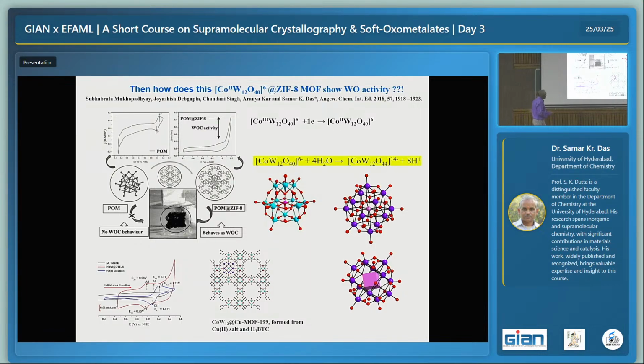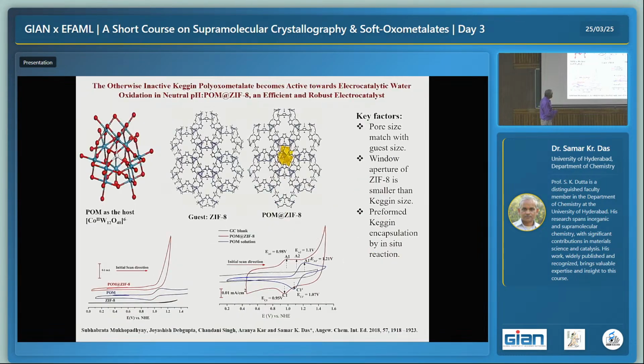So we believe that this is the compound formed, and that gives both couples, cobalt 2/3 and 3/4. Now it makes sense why upon encapsulation it gives oxygen evolution by electrochemistry, because we believe the cobalt cluster hydrolyzed to this cluster, and now this gives 2 couples, cobalt 2,3 and cobalt 4,3 and cobalt 3,2. Now you may ask me, how do you know this compound will give these 2 couples? Because now it is published by others. They synthesized this compound and did the CV of that compound, and it gives exactly the CV we got here. That means definitely in our earlier paper, although we thought it was that cluster, CoW12O40, it is not O40, it is O44.